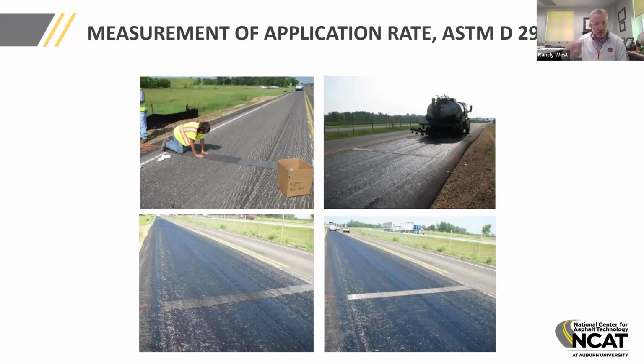On part 1 of the project, where we were building test sections, we used a technique to measure the application rate. It's an ASTM method, ASTM D2995. And it's probably a technique that's not used widely. At least I know some people are probably familiar with it, but basically it's putting out geotextile fabric, a non-woven geotextile fabric cut into squares, or you can use carpet squares. There's some guidance in the ASTM standard about how to do that. But you can lay these across the width of the lane that's being tacked. You can do them also in the longitudinal direction. But it's a good way to actually measure the application rate.